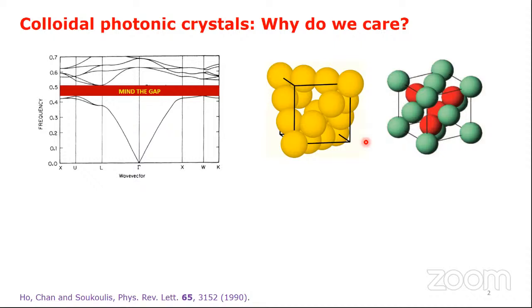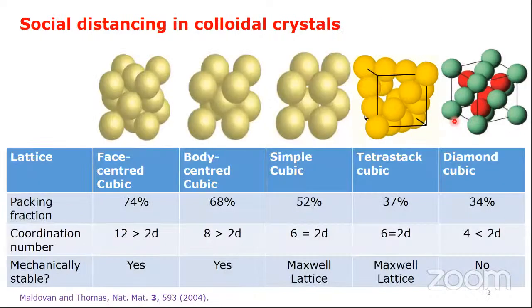Our focus here is on tetrastack and diamond crystals, the cubic polymorph of which were known to support a complete photonic band gap for a relatively low refractive index contrast. Let us take a close look into this series of cubic crystals starting from the face-centered cubic on the left. The packing fraction gradually drops with a decrease in the mean coordination number. Going by the Maxwellian counting rule, when the mean coordination number falls below twice the dimensionality, the lattice becomes mechanically unstable for isotropic colloidal particles.